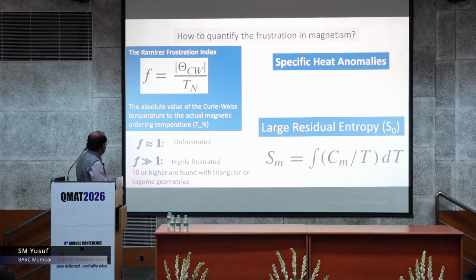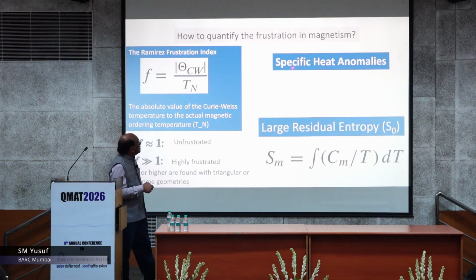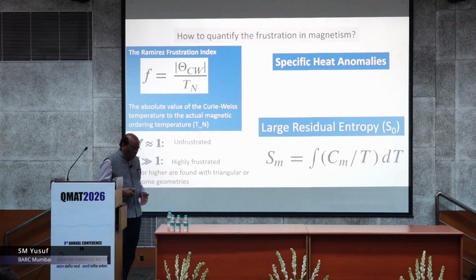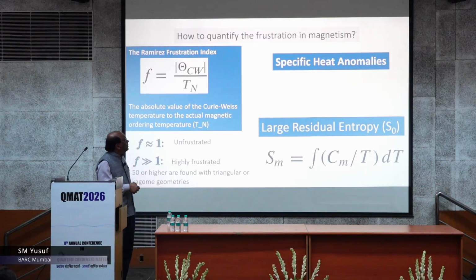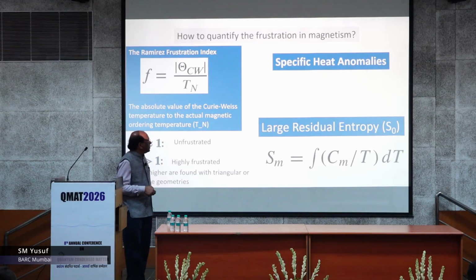Even values of 50 have been observed experimentally in Kagome lattices. There is another way of looking at the existence of frustration in magnetic materials: look at the anomalies in the specific heat. Specific heat should show a peak wherever there is a magnetic phase transition, but if you see some deviation from that, that could be yet another signature. And a very important thing is the residual entropy, which can be large.